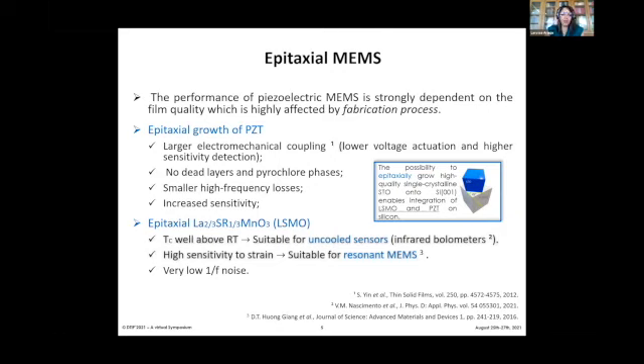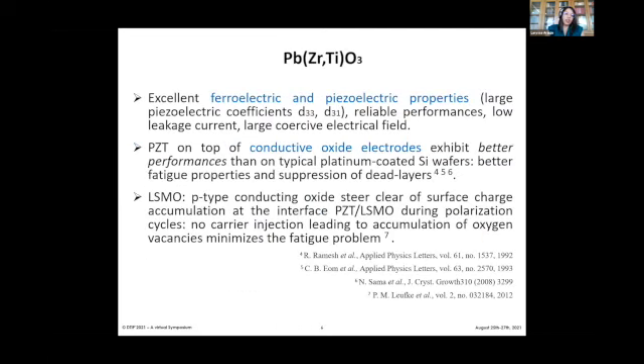For the PZT itself, it's a well-known material for piezoelectric actuation. But when we grow it epitaxially, we're going to have larger electromechanical coupling. So we can actuate it with a lower voltage and detection with a higher sensitivity. And the composition here, the whole stack, by using the PZT and the LSMO associated, is because the literature has shown that PZT, when it's on top of conductive oxide electrodes, it exhibits better performance itself instead of platinum electrodes. That's the main topic that we see with PZT in literature.